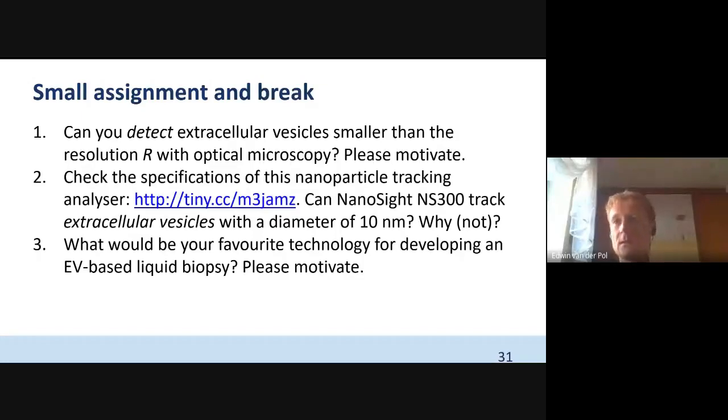Polystyrene, I will write it down just like in the classroom. No, 1.1 is too low. Water depends a little bit on the wavelength, of course, but at visible wavelengths you can fairly state 1.33. Thank you. Now, the contrast between polystyrene and water seems low, but it's fairly high actually, and that causes the light to scatter. Now, if you take an EV, the refractive index is the highest which we measured, 1.40.